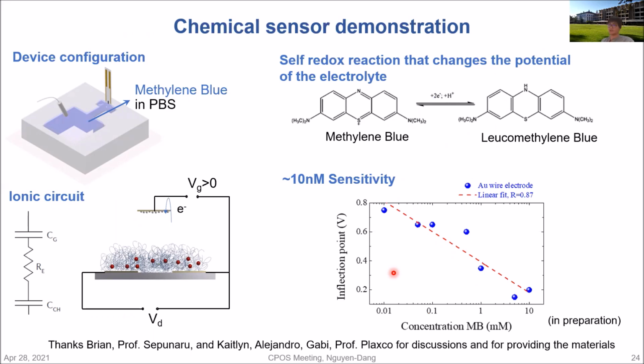And in terms of application, I demonstrated the use of the OECT made with this new fabrication technique in a chemical sensor. So basically, we measure the concentration of methylene blue in PBS. The device consists of the source and drain and a gate, divided into a two-compartment channel, with a well of PDMS, as you see here, and for the electrolyte, we use methylene blue in PBS. So the fundamentals of this sensing, the working mechanism of this sensing, is the following. Here on this schematic, you have the migration of ions into the film, and then you have the accumulation of anions into